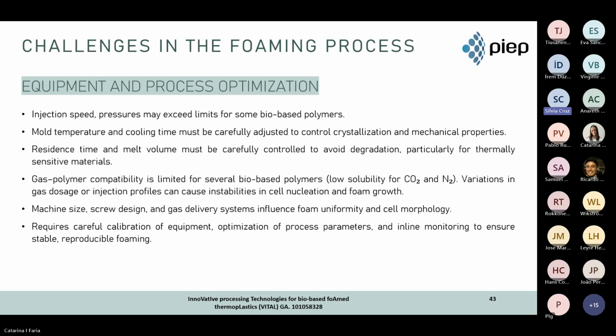Gas-polymer compatibility is limited for several bio-based polymers. Variation in gas dosing and injection profiles can cause instability in the cell nucleation and foam growth. Machine size, screw design, and gas delivery system also influence the foam uniformity and cell morphology, and require careful calibration of equipment, optimizing the process parameters, and inline monitoring to ensure stable and reproducible foams.